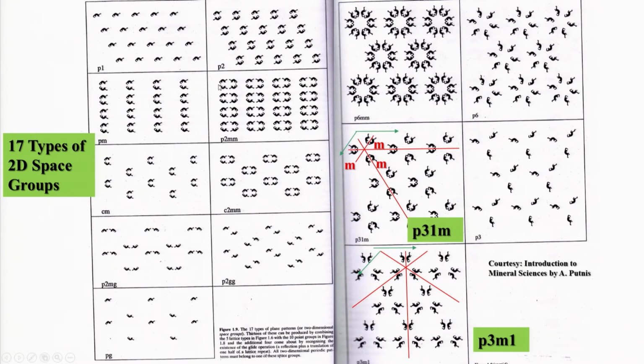So, once you generate this particular grouping, you can translate along this direction, along A direction. That means, if you have the center here, you come here. So, this 4 dinosaur unit can be translated along this and also can be translated along this. This distance is B, this distance is A, and A is not equal to B, and you have a rectangular plane lattice here. This has been generated because of this combination of primitive lattice and also the 2 mm point group of symmetry under the rectangular plane lattice group here.